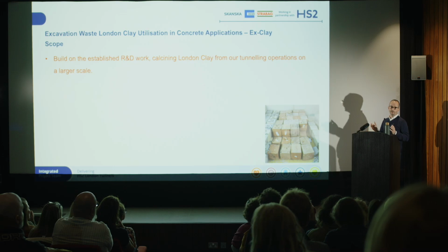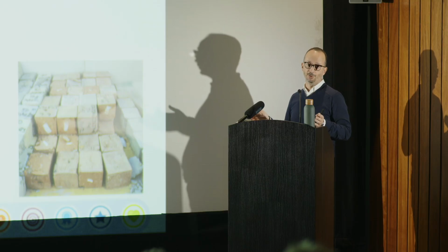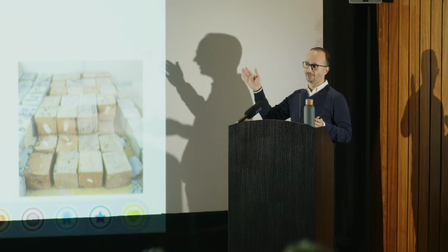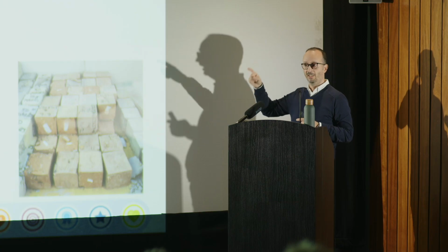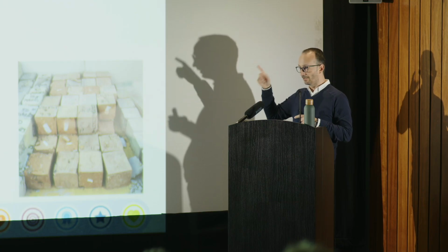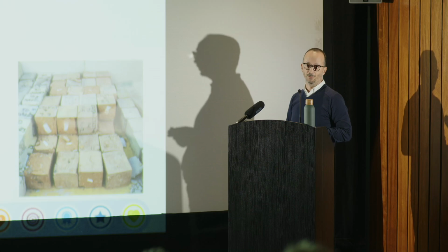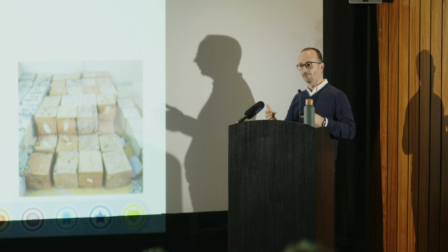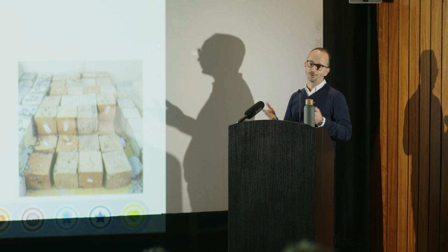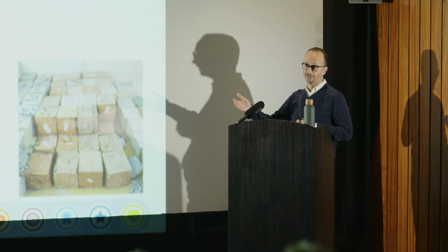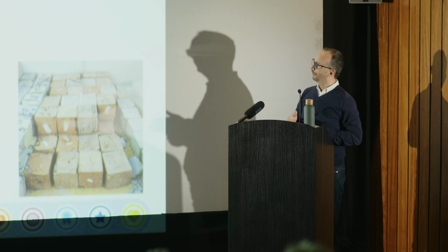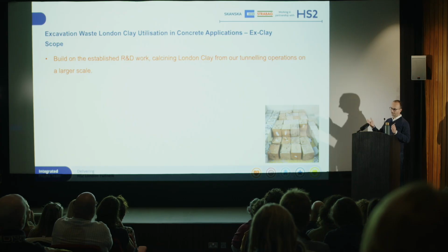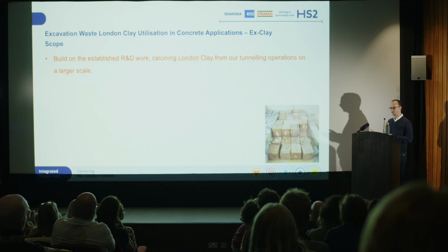One of them was the clay needs to be less than 5% moisture content. Now we'll see some pictures. The clay that comes out of the tunnels with the foaming agents, the water that goes in, is about 40% moisture content. And when we started looking into who can dry it down to 5%, there was no one that could do that consistently, that we can put it in the kiln. Now the second problem was, after you calcine it, you have to find a facility to grind it. That was difficult as well, even though we could find some alternatives, but it was a problem.